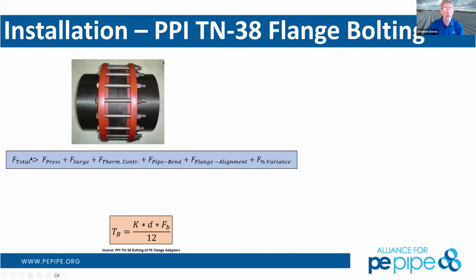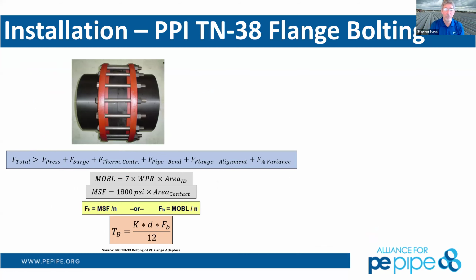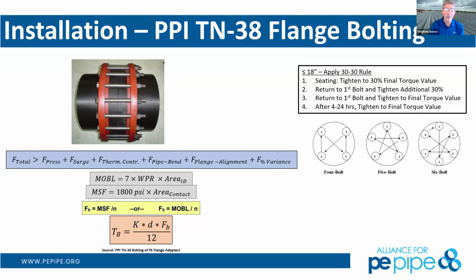So what you want the bolts to do, the bolts have to overcome the pressure, the surge, any type of thermodynamic or temperature contraction or expansion, any type of bending that might occur, flange alignment, and then whatever variance you want to take into account. The force in these bolts has to be greater than all these other forces trying to pull that apart. So once you go through that calculation, you can see that there's a certain torque value that you need to put on all these bolts to make sure that you get the right contact area and you get a fully sealed flange. Now, the nice thing about polyethylene is that with a polyethylene to polyethylene flange adapter joint, you don't even need to use a gasket as long as it's aligned properly and the bolts are torqued properly.